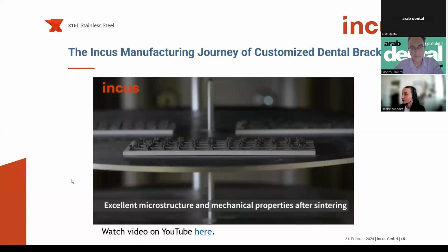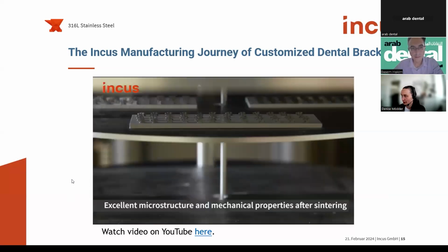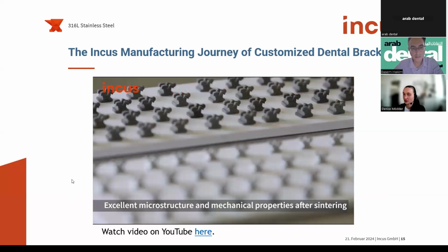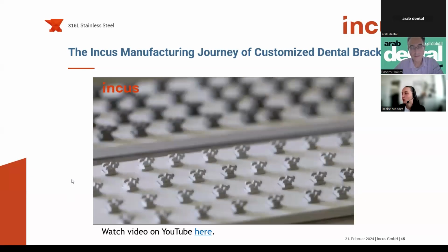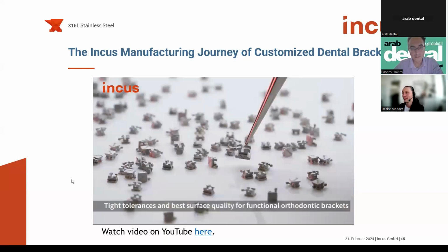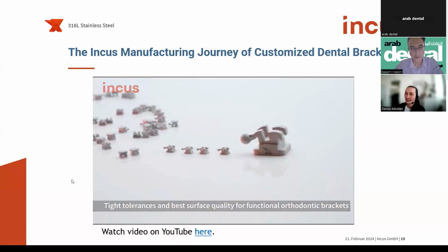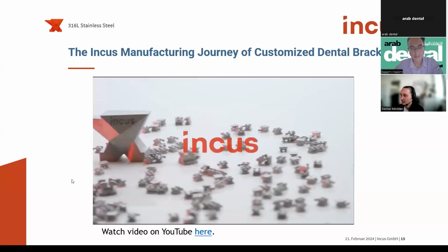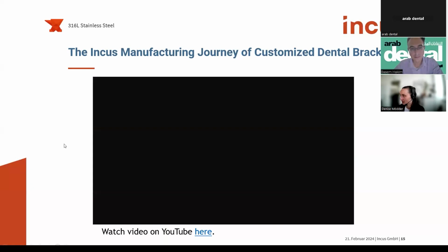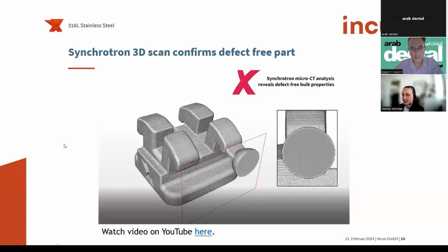Since the metallic brackets are really small, the time for sintering is also not long and can be reduced. While we have the experience with parts going from small brackets to much bigger parts, we do believe reducing the time for the brackets is definitely possible. Here's an image of a synchrotron 3D scan, or CT scan, of one of our demo part brackets, and you can really see inside that the porosities are close to nothing.